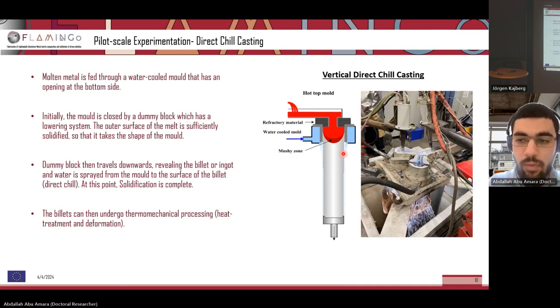And you can see this is an image of the direct chill casting facilities at Brunel. Here you can see the hot top and the aluminium melt, and this is the water for cooling the billets. And this is one of our composite castings, actually. We had applied ultrasound in different areas in the launder and the hot tops for dispersing the particles. So as I mentioned before, we wanted to apply the metal matrix composites technology in direct chill casting in order to move forward in industrializing the aluminium metal matrix composites technology.